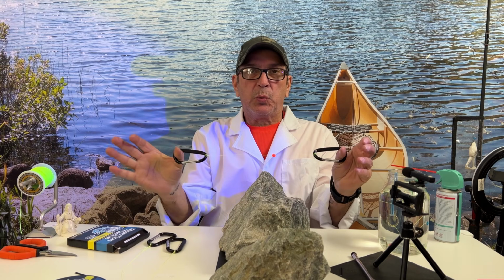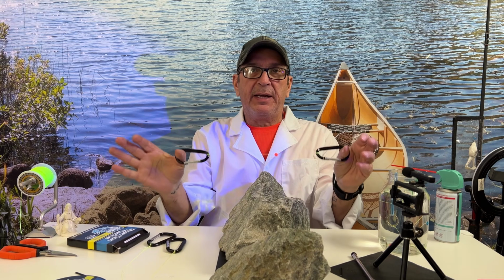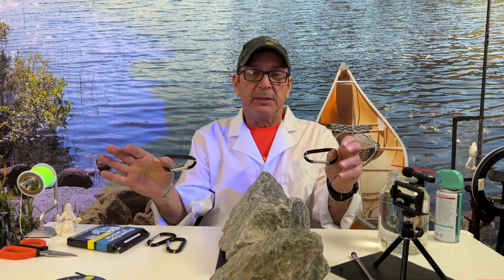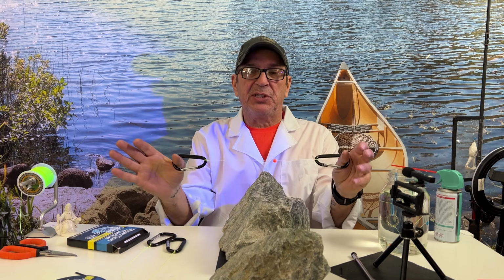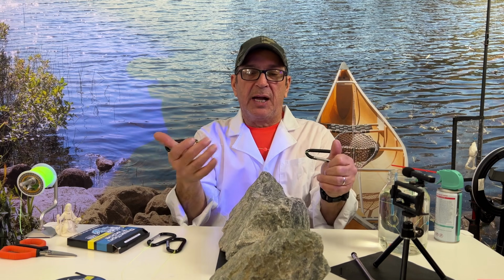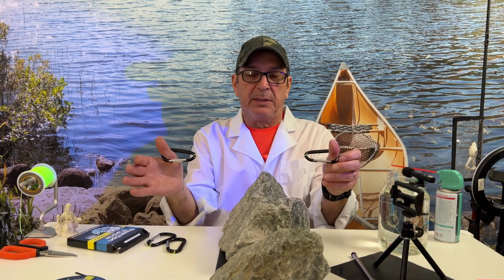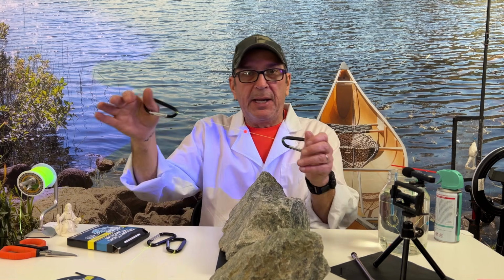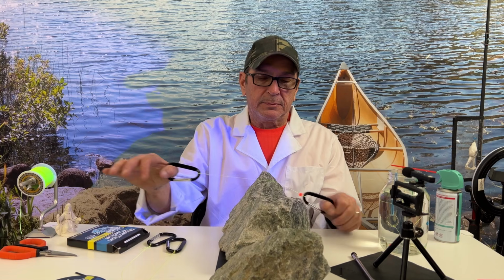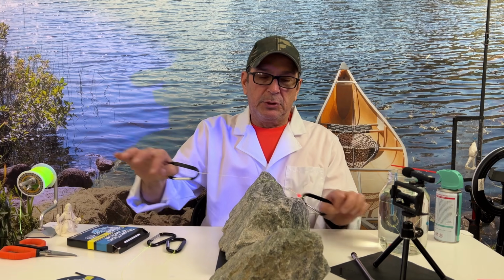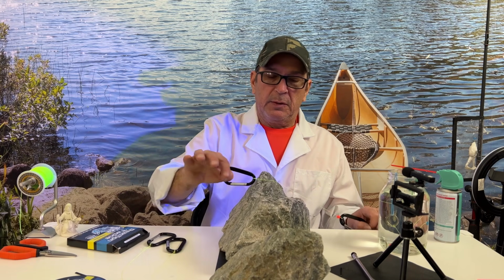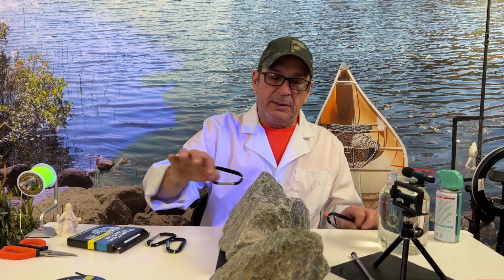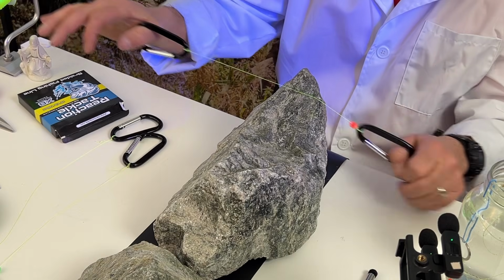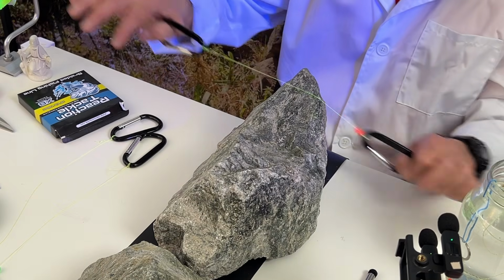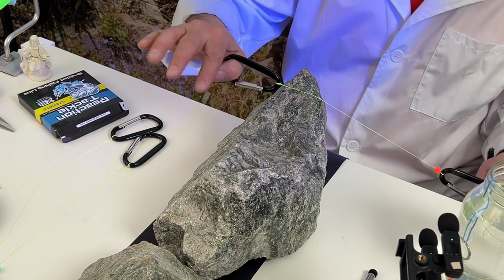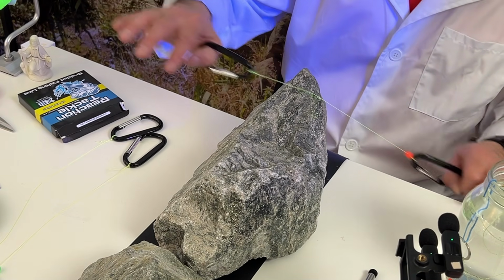Here we go with test 1 of the 20-pound braided Reaction Tackle fishing line, testing for abrasion resistance. This is the dry fishing line represented by the orange fishing bead. Down and up is 1 cycle. 1, 2, 3, 4, 5, 6.